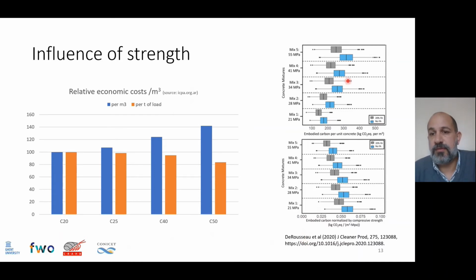And here we see an investigation from de Rousseau and co-authors, in which, of course, when they design concrete, conventional or with fly ash, for a higher compressive strength, we have a larger embodied carbon per cubic meter of concrete because we need more cement. But when we compute the embodied carbon normalized by compressive strength, we observe that the lower compressive strengths are the mixes that have the largest embodied carbon. So again, this is showing how moving towards higher compressive strengths can help in achieving more efficient use of cement and concrete.